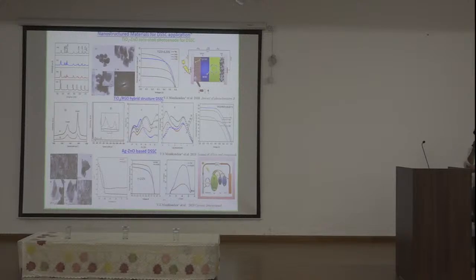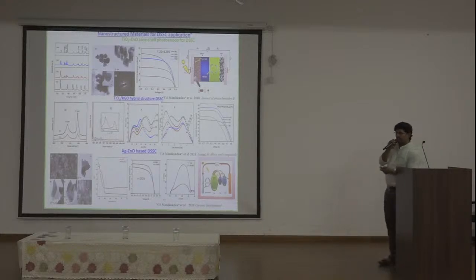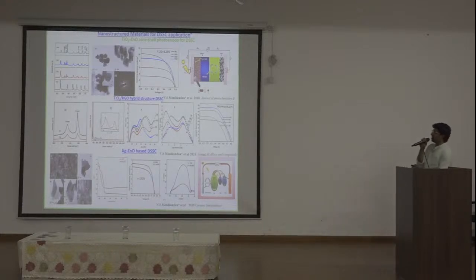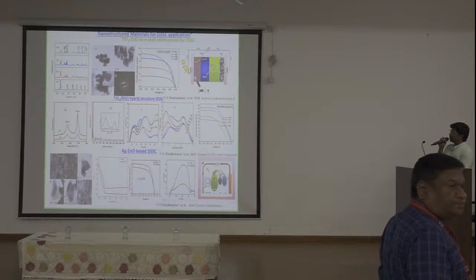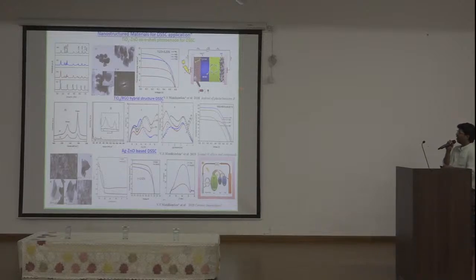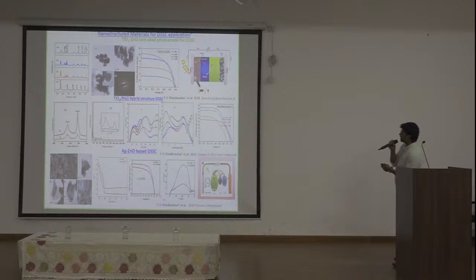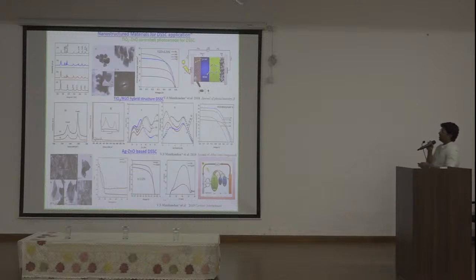After injection of the electron from the dye to the semiconductor material, the back electron transfer is highly reduced, which we can see as the short circuit current density slightly increasing with the inclusion of ZnO. Once the electron is injected into this semiconductor material, the ZnO acts like an energy barrier. So the back electron transfer reaction is highly inhibited. That's why the short circuit current density is increasing, and that's why we get a maximum efficiency of 3.25.